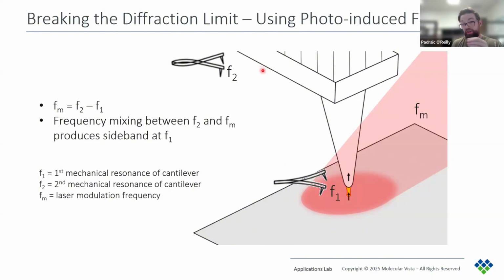And the PiFM signal is generated using frequency mixing. So one of those frequency signals comes from the cantilever being oscillated at its second resonance mode. The other frequency is from the IR laser. And the frequency used for this is chosen so that a sideband is then produced that matches the first resonance mode of the cantilever. And therefore, any changes in the PiFM signal at this frequency is detected by the tip and then amplified by this first resonance mode.